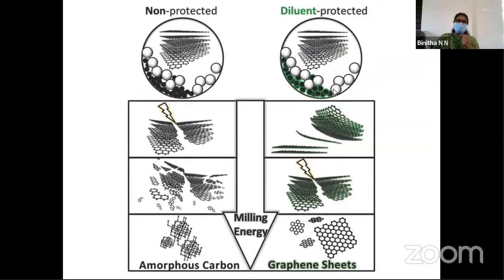This is the process for non-protected ball mill exfoliation of graphite. We can see the graphite sheets are broken there, and finally it will result in amorphous carbon. So it is not so recommended. But when we use protected exfoliation of graphite in the presence of other milling agents, shear force dominated exfoliation of graphite occurs, and we will be getting high quality graphene sheets.